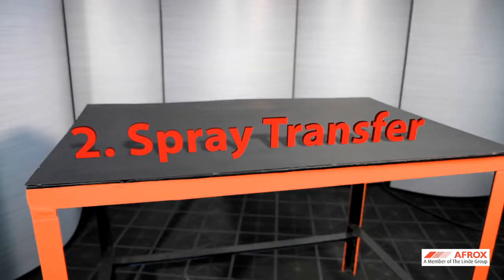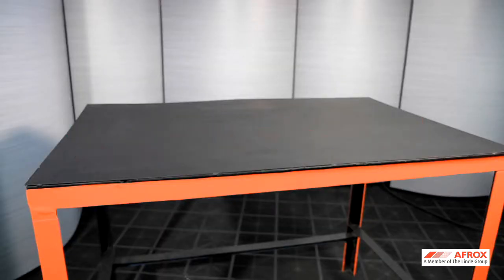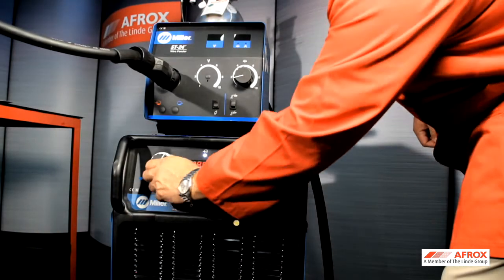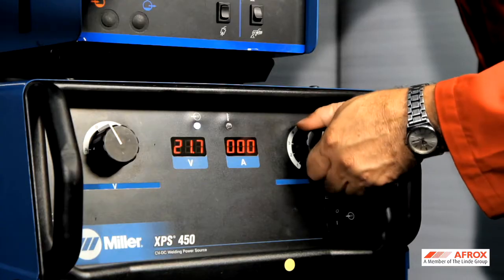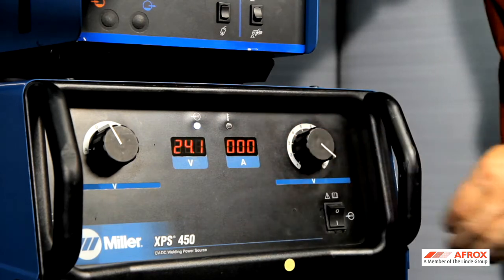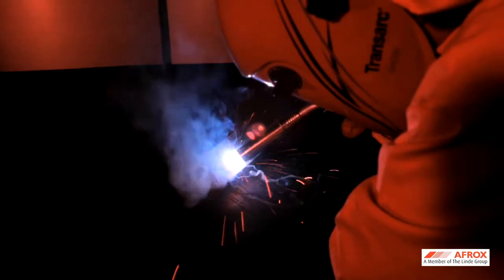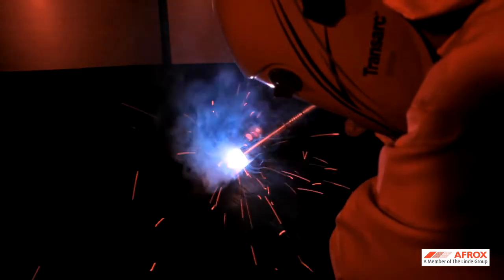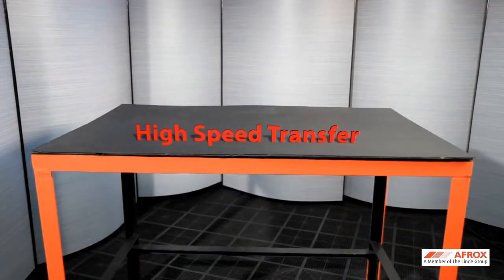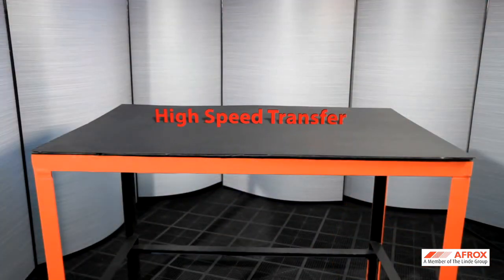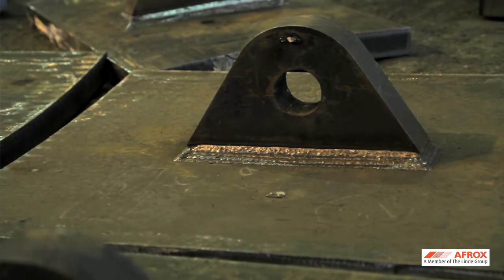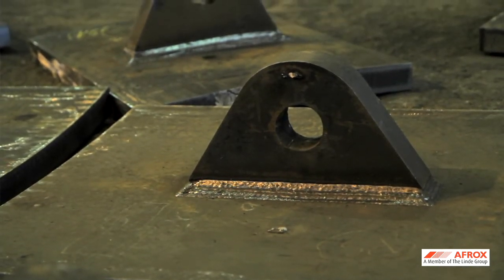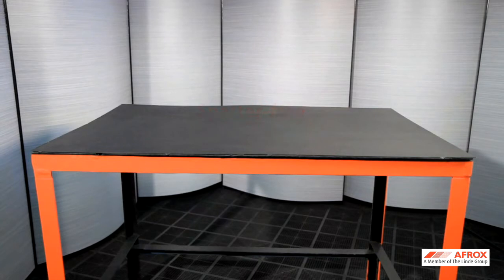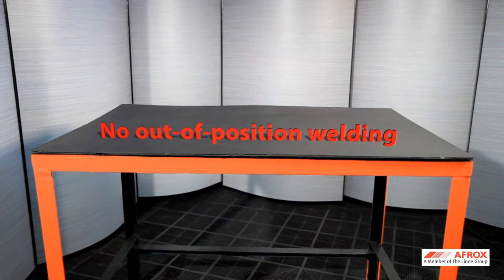Number 2. Spray transfer. The voltage on the power source is set between 24 and 32 volts. The wire feed speed is set until you hear a hissing sound with very little visible spatter. The major advantages of spray transfer is the high speed of this transfer, better weld penetration on thicker materials, and a virtually spatter-free weld. The disadvantages of spray transfer is that it cannot be used on thinner materials and out-of-position welding.